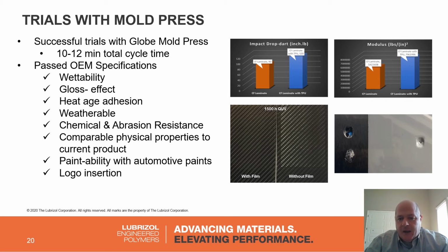Additionally, again, depending on the construction, we have seen a modulus increase in the overall construction on the order of about 20 to 25%, which again, if the whole point of using carbon fiber is for strength, if you can make that existing carbon fiber stack up or build up of material stronger, then again, you could further potentially reduce weight.